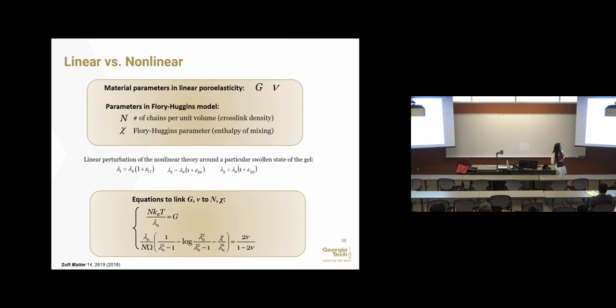And then what we did is compare this nonlinear theory with the linear theory. With the shear modulus and Poisson's ratio we can measure from indentation, we want to extract the thermodynamic parameters. N is related to crosslinker density. Chi is the interaction parameter, describing the enthalpy of mixing. What's the chemical affinity between the solvent and the polymer?